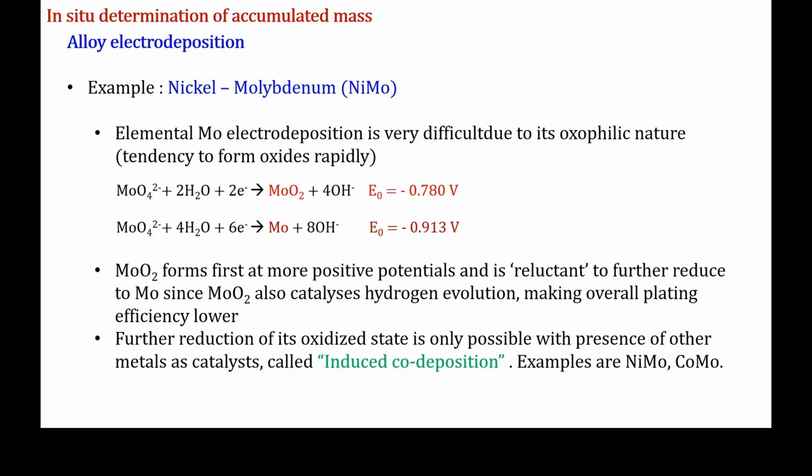So Namkang is currently trying to understand how to get elemental molybdenum rather than the oxide form, because it's quite difficult to distinguish between the two using XRD. And so quite likely you get molybdenum oxide forming preferentially before you get to molybdenum, but you can't tell from the measured current whether you've had that conversion from molybdenum oxide to elemental molybdenum or not. So Namkang is now using a mixture of electrochemical quartz crystal microbalance and looking at the deposit using scanning electron microscopy and energy dispersive spectroscopy to try and actually see what the composition of the deposit is.